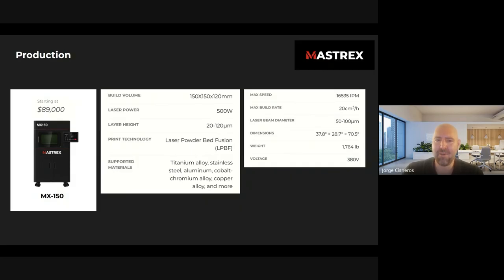And one final thing to note for this one, it has listed voltage of 380, and that's triple phase. So that's industrial voltage, and it can actually run anywhere from 208 to 480. And that's something that we would set up during the time of ordering. So it requires a little bit more infrastructure. However, as far as footprint goes, you can see we've got it listed there in inches. It's about 3 feet by 2 foot footprint, and it's a full height machine, so it's not going to sit on a table. So it's still overall a very small footprint for the build size that you are getting.